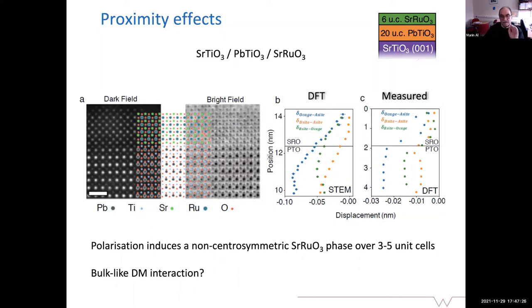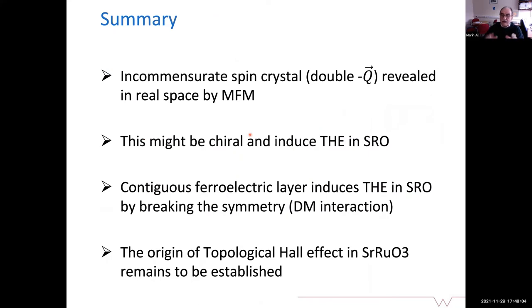by scanning transmission electron microscopy. And we see that indeed it follows, not exactly like the DFT, but you wouldn't actually expect that, but it's a significant distortion of the initial symmetry of the strontium ruthenate, and that induced a non-centrosymmetric strontium ruthenate. We can call it polar strontium ruthenate if you want, but definitely that will induce a bulk-like Dzyaloshinskii-Moriya interaction. And that would be sufficiently high just to tune locally the magnetization swirling and give us this incommensurate spin crystal, which we have revealed in magnetic force microscopy.